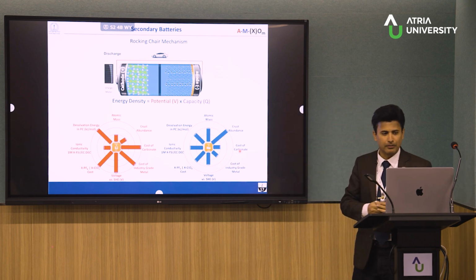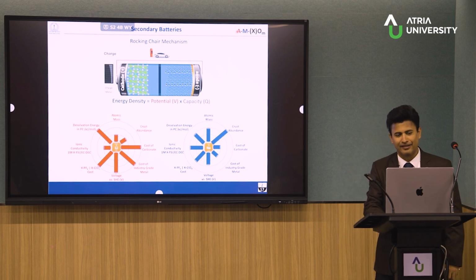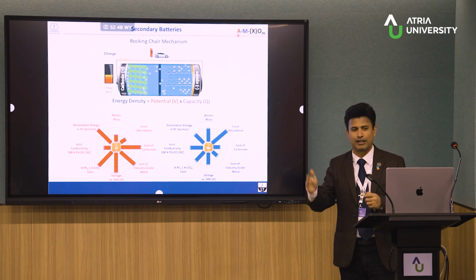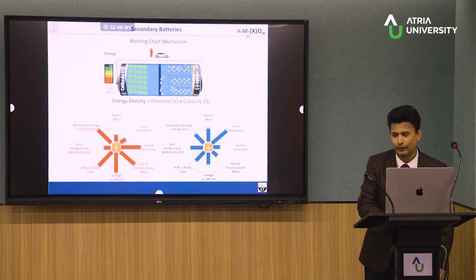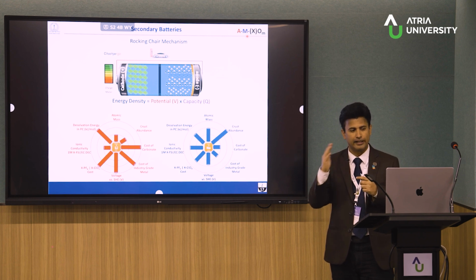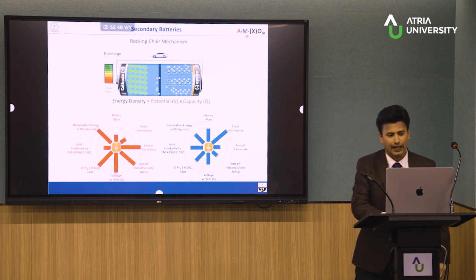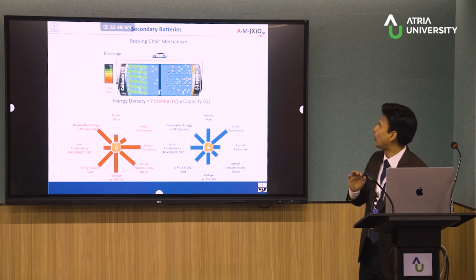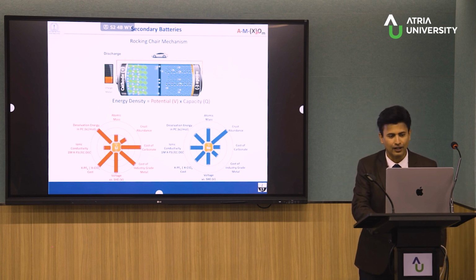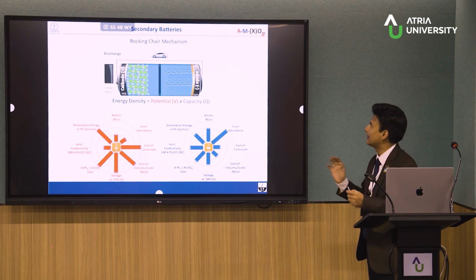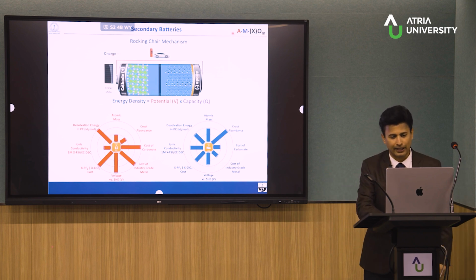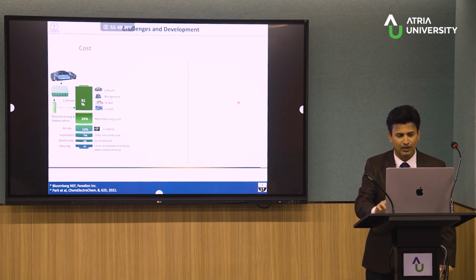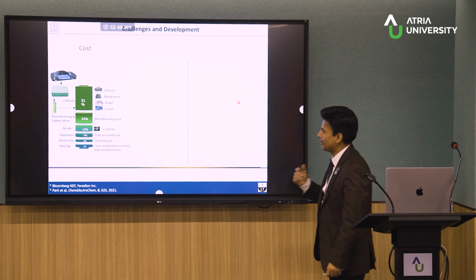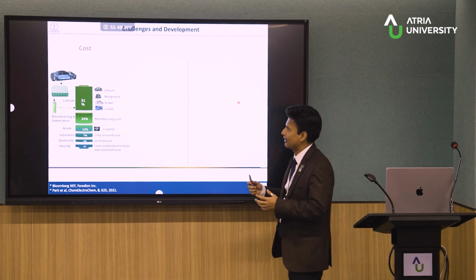Now, when we talk about battery material, any cathode material, essentially has an alkali element, lithium or post-lithium, sodium, potassium, and so on. We have a transition metal which changes the redox state, cobalt, nickel, iron, manganese, and so on. And we have either oxygen to form an oxide cathode or one extra anion called a polyanion. So this is the classic composition, and here I am talking about the A, which can be either lithium or post-lithium like sodium battery.